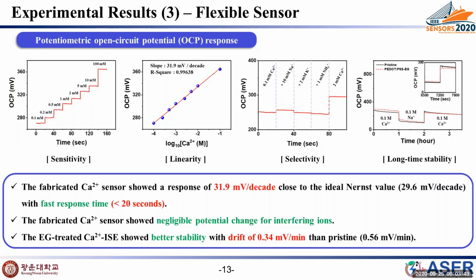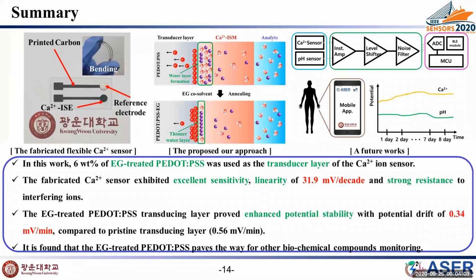Finally, to confirm our research can improve the stability, a long-term potential stability test was performed. From this test, the EG-treated calcium ISE showed better stability with a drift of 0.34 millivolt per minute. I summarize my presentation.